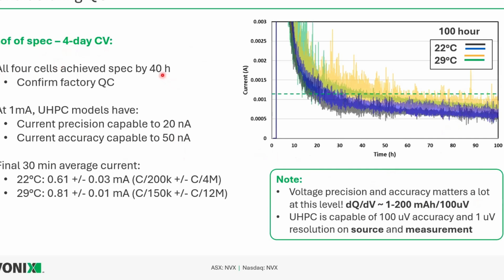By about 40 hours, we confirmed this kind of factory ideal QC. All the cells came under this. Well, the line is not where it should be right now, but they came under this 1 milliamp point here. Even the 29 degree and 22 degree cells were both under that line. So that's what we're assuming is this ideal QC ability. So even now we're saying just in 4 days, instead of say 2 weeks, maybe we're able to do this when we connect a cell to UHPC.